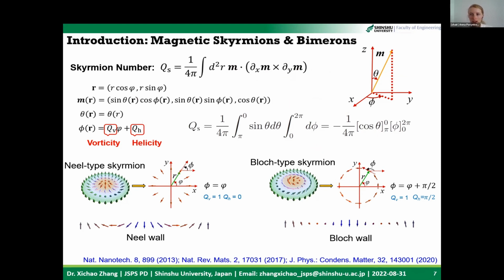The next question is, does the Dzyaloshinskii-Moriya interaction exist without heavy metal, meaning inside some insulator? Basically, I think there are two groups of people working on DMI materials. Some work on systems where the DMI is induced at the interface in a multilayer, and some work on systems with an asymmetric lattice structure. So the DMI is generated due to the broken inversion symmetry in the materials.